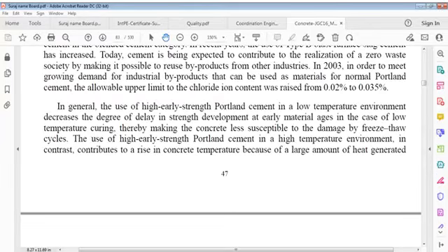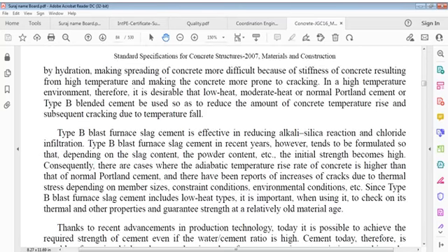In general, use of high early strength Portland cement in a low temperature environment decreases the degree of delay in strength development at early age. Where the temperature is low, high early strength Portland cement is a good choice, and in the case of low temperature curing, it makes concrete less susceptible to damage by freeze-thaw cycles. Use of high early strength Portland cement in a high temperature environment, in contrast, contributes to a rise in concrete temperature, makes placing more difficult because of stiffness of concrete, and makes concrete more prone to cracking. Therefore, it's desirable that moderate heat or normal Portland cement or type B blended cement be used so as to reduce the amount of concrete temperature rise and subsequent cracking due to temperature fall.